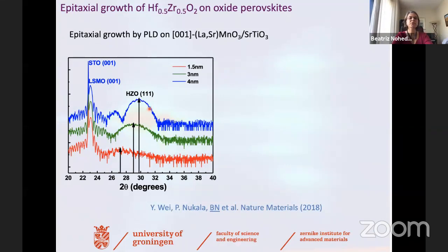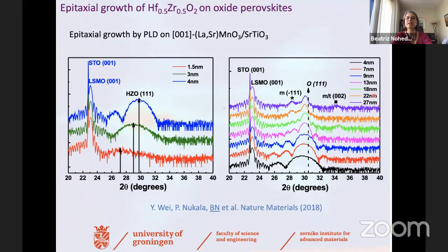So first of all, the materials, when they are very thin, are under a huge compressive strain. You can see how the strain relaxes. This is an X-ray diffraction pattern showing the strain relaxation of the material. And they are pure phase until thicknesses of about 10 nanometers, where you can see the monoclinic phase, the ground state, non-ferroelectric, non-polar phase appearing.